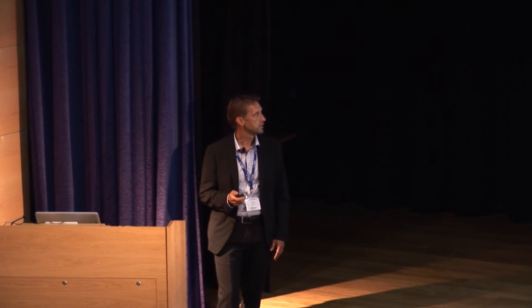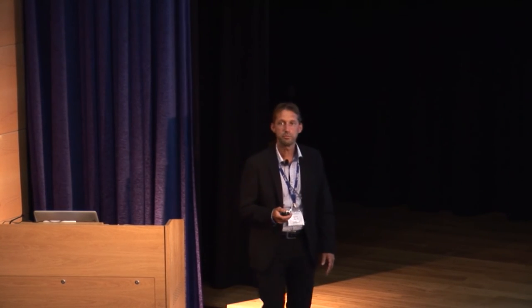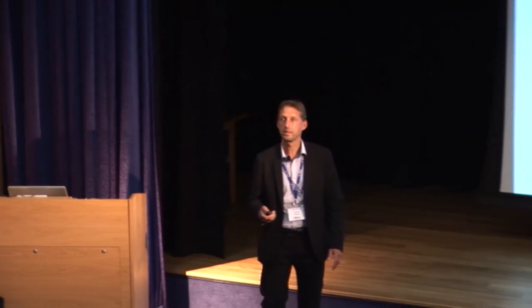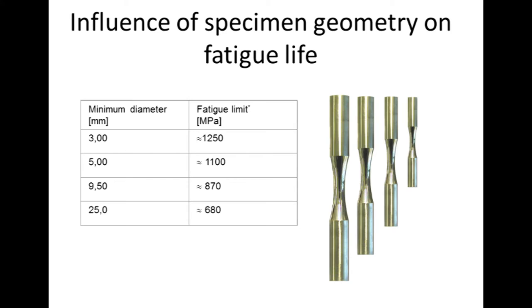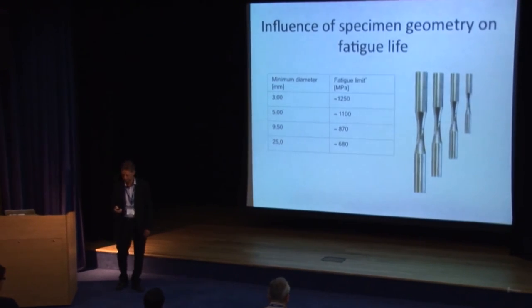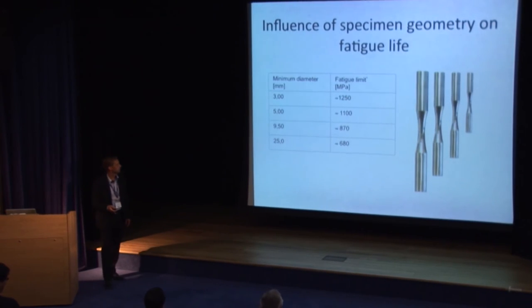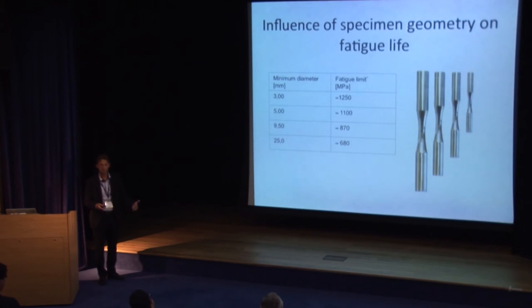We made a quite fun test, which was very simple but quite illustrative, I think. We know that the fatigue data you get differs depending on how big a volume you test. And sometimes people ask me, what is the fatigue limit? As I said, I just pick a number. And you see the reason. We took the same heat.